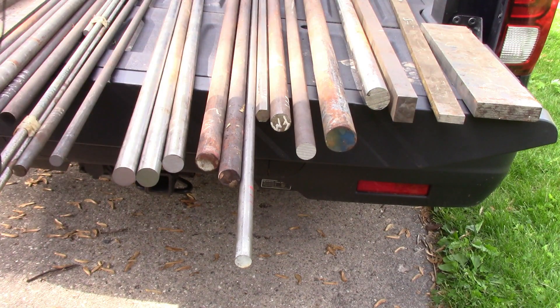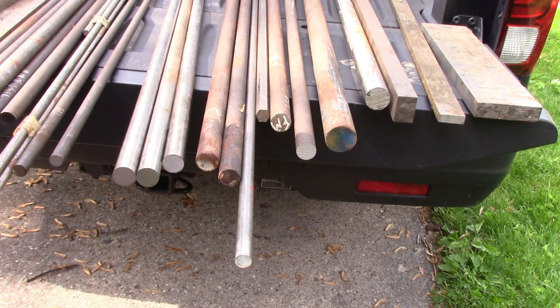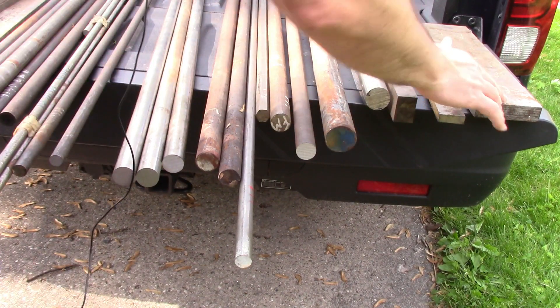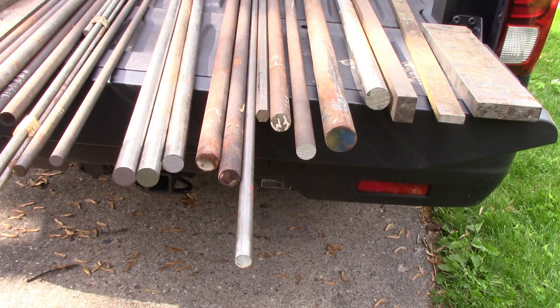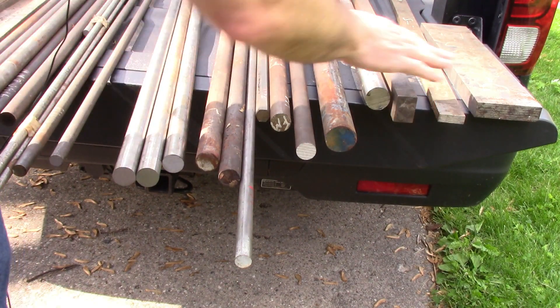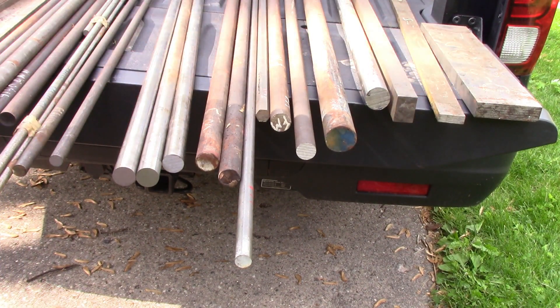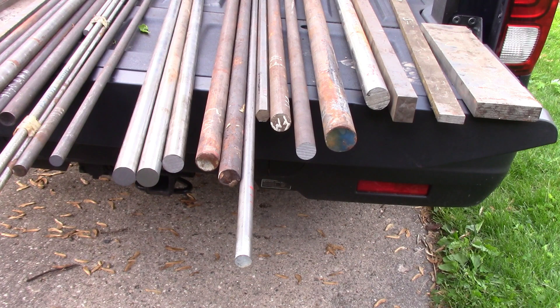The last two pieces I also got for my buddy Larry. We have a piece of S7 — half inch by inch and a half, about three feet long — and then this is a nice big chunk of D2. Those are both really nice tool steels. S7 is a shockproof steel, so you see it used in things like cold chisels and jackhammer bits — stuff that's got to take a lot of abuse and sudden shock. Once it's heat treated, it can really take quite a beating. D2 is a die making steel; die bodies and things that are going to be forming or cutting are made out of D2. It's a little tricky to work and machine, it's very tough, but once you get it heat treated it stays put and doesn't wear very much at all. So it's fantastic for tool and die work. Larry's probably going to make some knives out of it and hopefully he'll make me one.